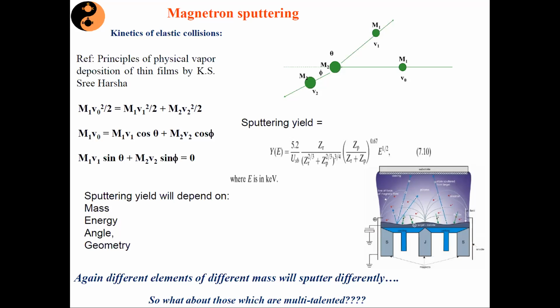So that is not possible, because if you have a pellet with yttrium, barium, copper, then again yttrium, barium, copper have different mass, so they will sputter at different rates, and hence they reach the substrate in different ratios, and hence the stoichiometry is actually not retained. So that is one limitation as far as magnetron sputtering is concerned.